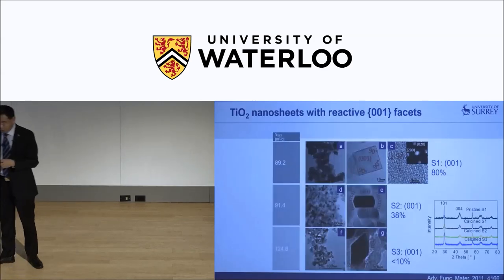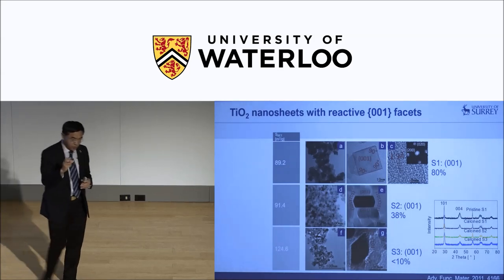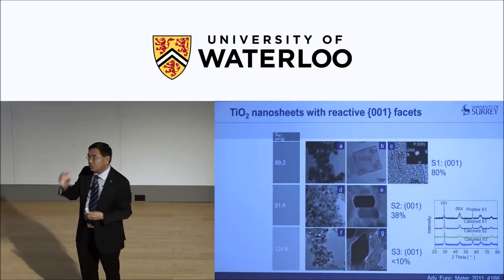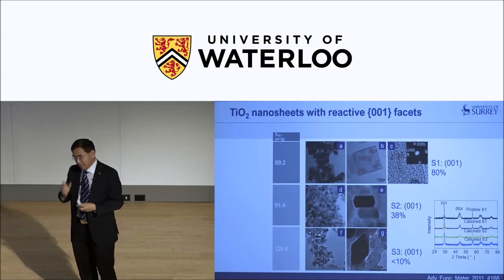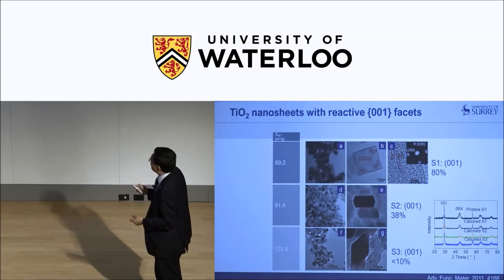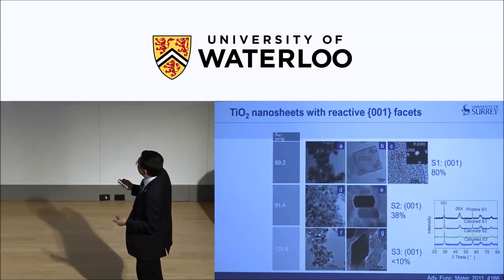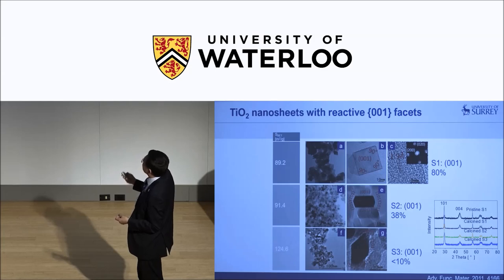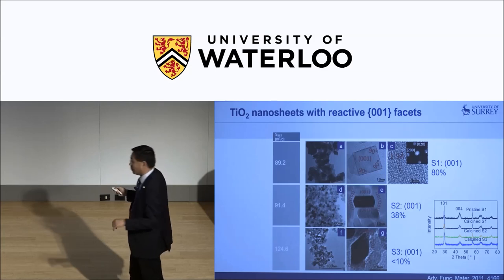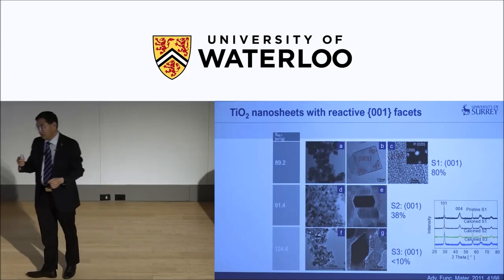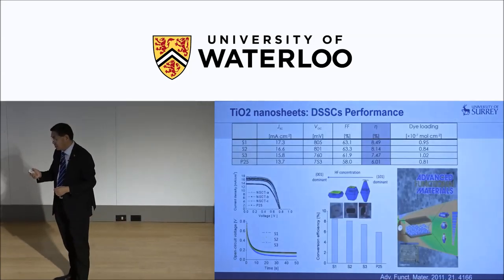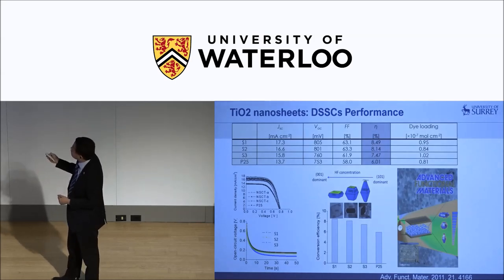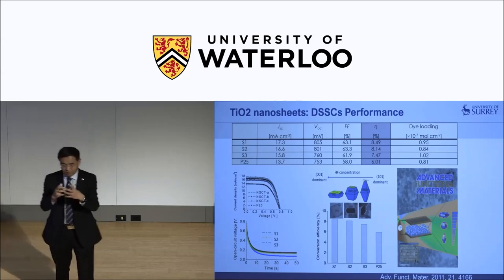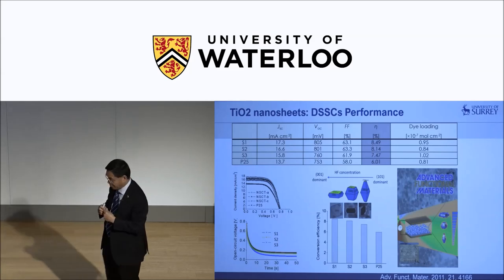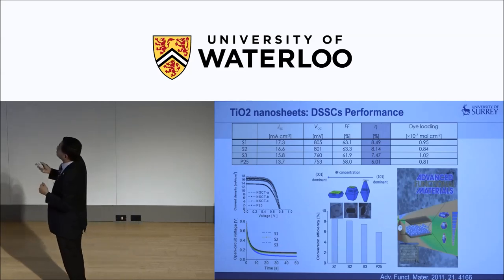We also did, just to demonstrate, control everything else being equal, to demonstrate the facets' reactivity in terms of the dye-sensitized solar cell. You can control the percentage of the 001 phase from 10% to 38% to 80%. Three samples, simple. And then you make the photoelectrode and test that. And my students did this, and you can see there's a clear trend that when you have more, this is 80%, 001 facet dominated crystals, and you make this electrode, and it's more efficient. Right.